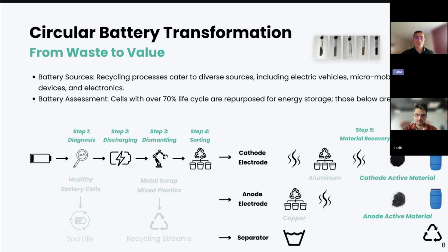In the second step, we discharge the batteries in order to deactivate them so that they do not explode when we're handling them. But at the same time, with the discharging, we're collecting all the lithium on the cathode side to have a selective recovery of the lithium at the end of the process. In the third step, after the discharging, we're dismantling the battery cells. So we're now going into the dangerous zone where we're opening the battery cells and separating the anode, the cathode, and the separator from each other. And this is done automatically with an own developed machine that is able to do that in a safe manner, so that no operator has any involvement in this process step.